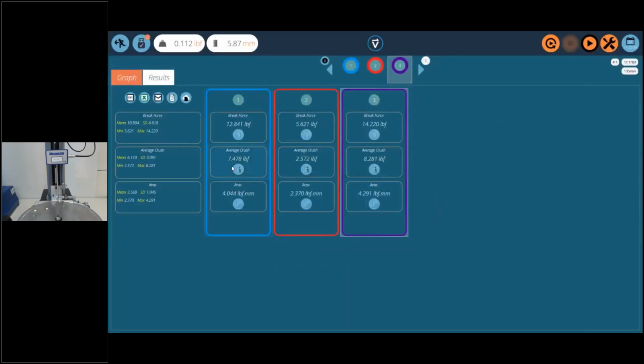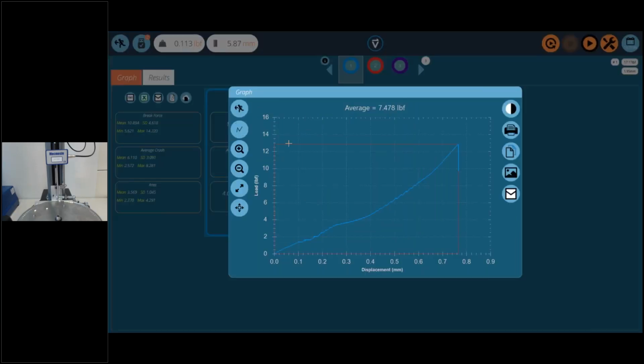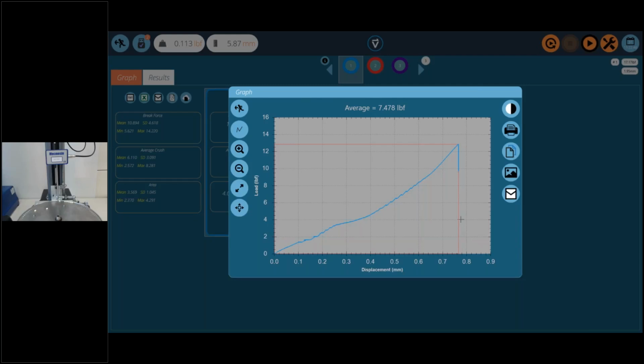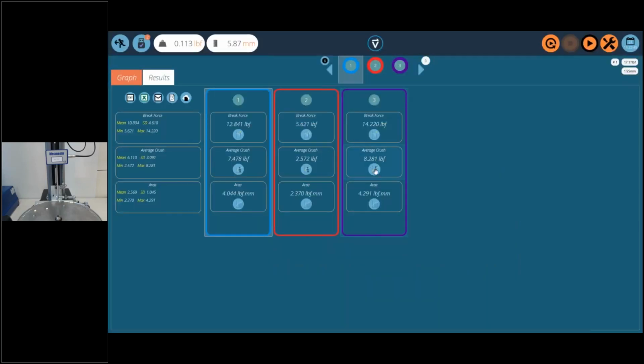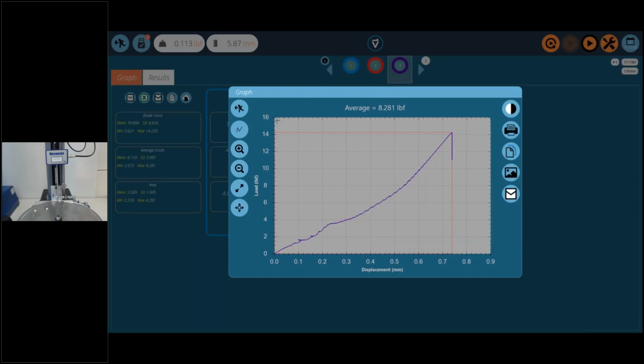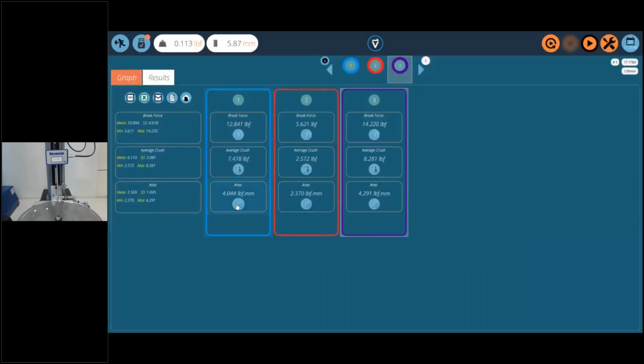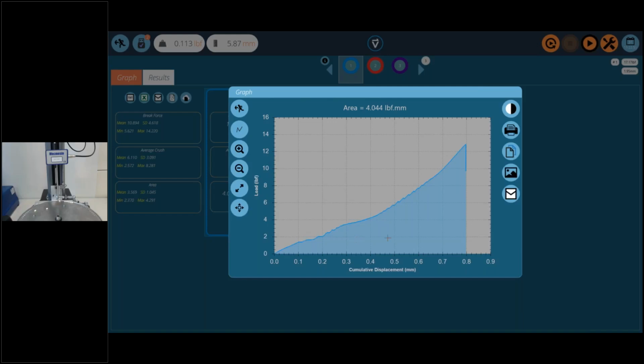And then we did also measure the average crush across the entire spectrum. If you can see my screen, that would be that red area, which is measuring about 7.4 pounds. That's the average, and it's seeing about 8.2 pounds in sample 3. And then we also wanted to look at the area under the curve, or the energy, and that's about 4 pounds per millimeter, based on the samples that we're testing. So this is a typical single pellet crush, where you're testing them one by one by one.